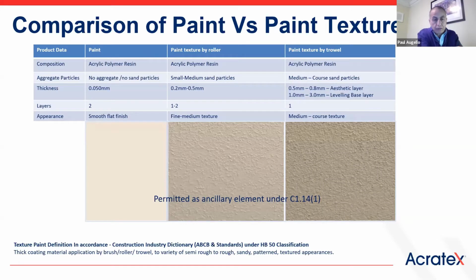So if you look at paint being the one on the left, it provides a flat finish as we know today, and that's generally put on up to about 0.05 millimetres, so a very thin layer. If you take the next layer up, which is a paint texture put on with a roller, these now have fine sand particles in them to give you a slight sand sort of finish. These are put on around about 0.2 to 0.5 millimetre, and can be easily put on with a roller. It's when you get into these more coarser finishes, where you've got coarser sand particles that cannot be put on with a roller, you need a trowel applied material because of the aggregate size to create the thickness and the finish that you need.